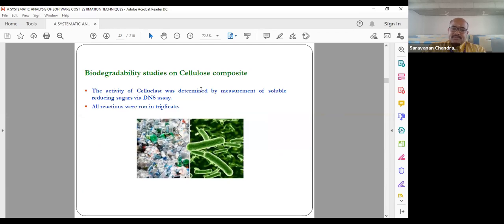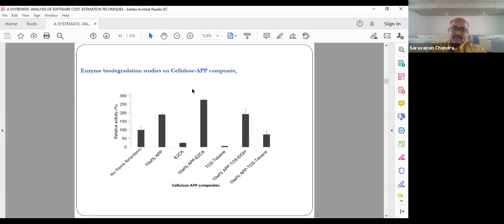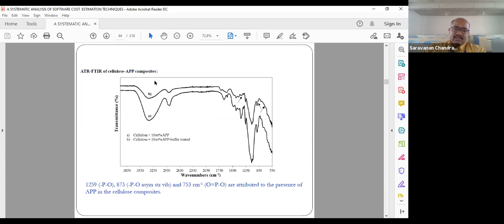Okay, the same materials we subjected to biodegradability studies with cellulase as the enzyme. Next slide. Next slide, ma'am. As you can see, with no flame retardant it is showing 100%, but at 10 weight percent APP it is increasing, because APP is ammonium polyphosphate. When it is in the enzyme solution, which contains a buffer solution, it dissolves and leaches out from the film, which gives a more porous film. Therefore, it increases the interaction with the cellulase enzyme, showing more activity. At the same time, with ETCA alone there is nothing.